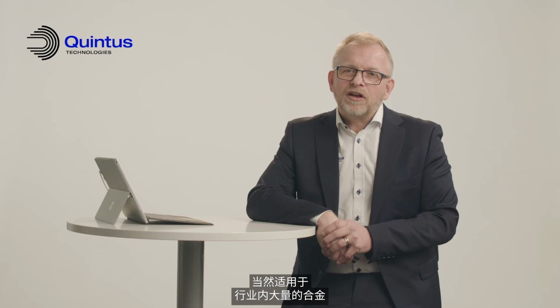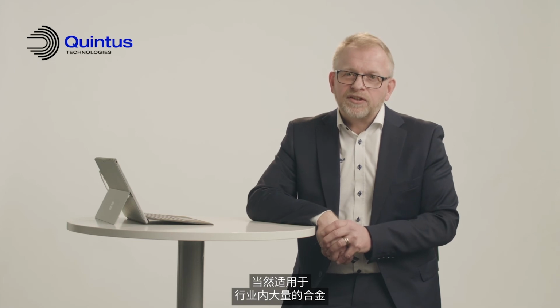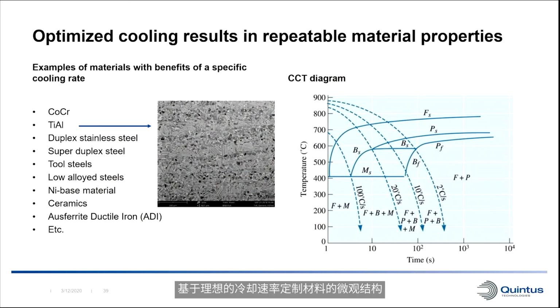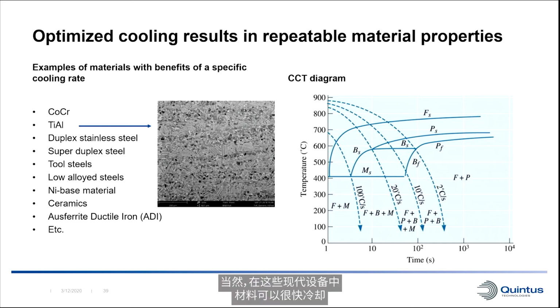And of course, for a large number of alloys in the industry, everything from castings, of course, to AM, can be heat treated in this way using HIP to remove the defects in the products and then tailor the microstructure of the material based on a desired cooling rate. And of course, the material can be cooled very, very quickly in these modern units, which means that you can basically achieve whatever you want to do with different materials.